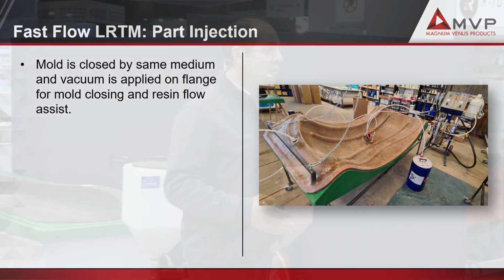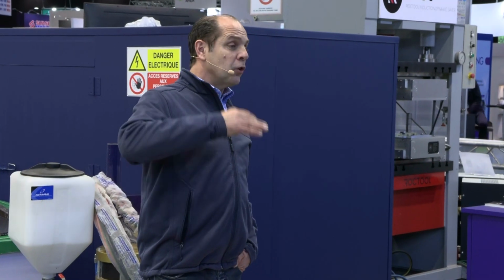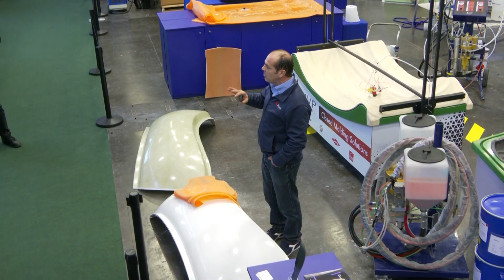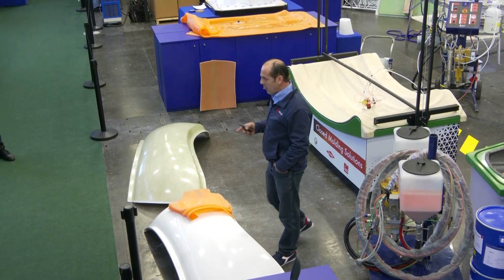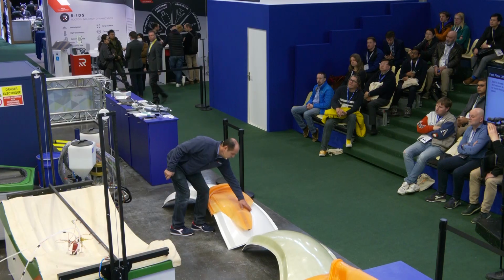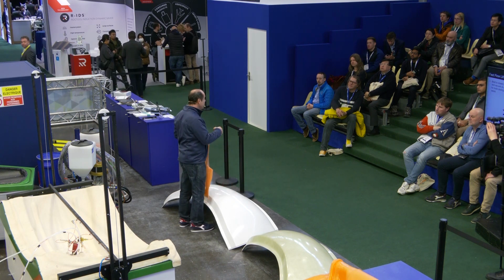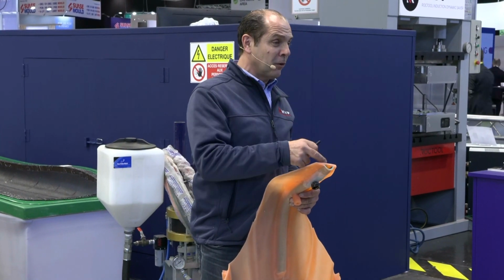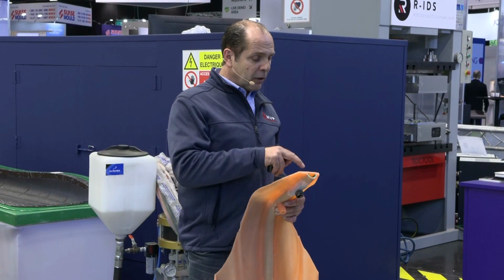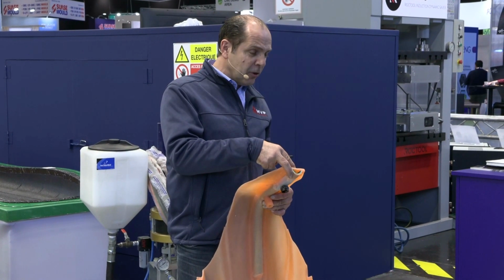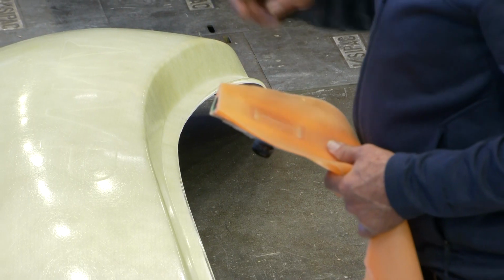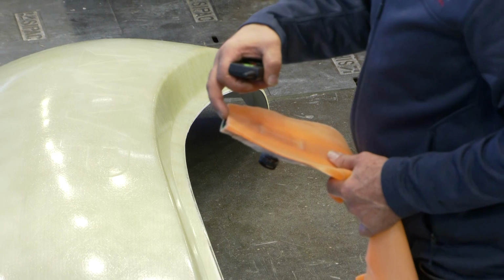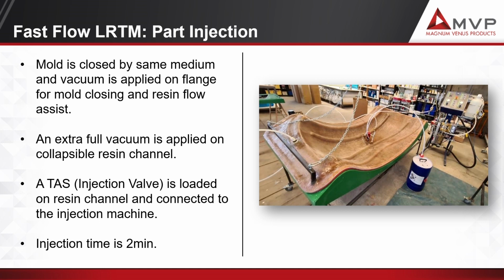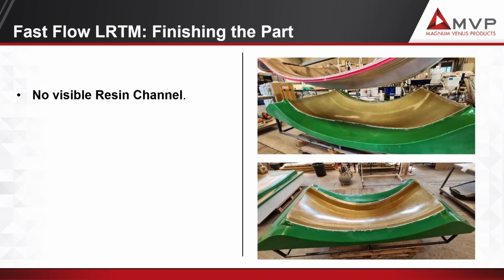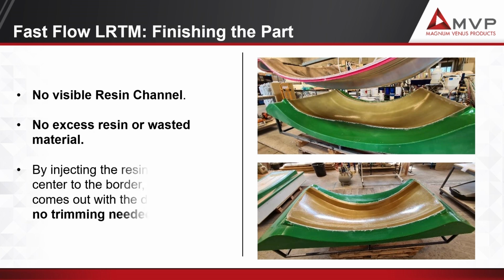When we use polyester resin, the resin contains styrene. So we cannot pull the full vacuum, if not the styrene will be bubbling. So we use like 60, maximum 70% of vacuum. But when we apply the vacuum into the resin channel, it cannot be the same vacuum. Because if you have the same vacuum on both sides of the silicone, nothing will happen. The vacuum you pull on the resin channel has to be higher than the vacuum you use to help the resin flow. That's why we use a medium vacuum, and full vacuum into the resin channel, to be sure that we collapse it. And then when you demold, as you can see, we demold a directly finished part.